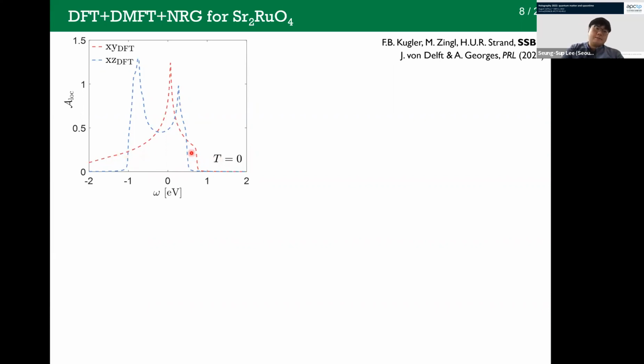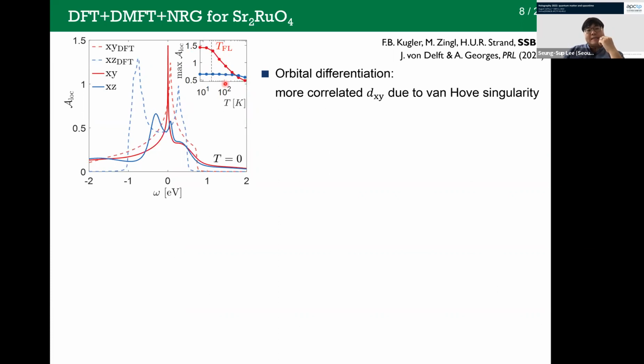And let's turn on strong correlations. So these are our DMFT plus NRG calculations. We see a very sharp quasi-particle peak of the XY orbital, which can be seen as the renormalization of the van Hove singularity of the original input to the DMFT calculation. On the other hand, the peak height for the other 2 orbitals, XZ and YZ, are suppressed compared to the DFT input. When you track down just the peak heights as a function of the temperatures, we see that the peak height for the XY orbital depends very sensitively on temperature, being maximal below 25 Kelvin. On the other hand, the peak height for these XZ and YZ orbitals are more or less stable as a function of temperature. So it means that the XY orbital is more correlated than the other 2.